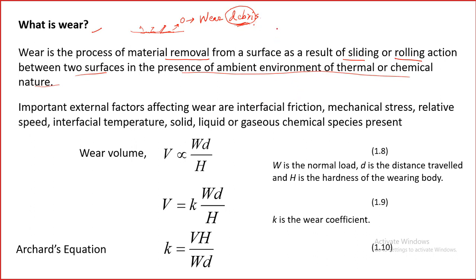So we know that wear is extremely harmful for any kind of machine because it will damage the components. Whatever bearing you have, let's say a journal bearing, if wear takes place, it will not work anymore because there will be a huge amount of vibration between the shaft and the bearing. Because of this vibration, the wear rate will go up and the whole machine may fail by fatigue. Although the machine failed by fatigue, the originator was wear. We always try to find the root cause of any kind of engineering failure, and the root cause is often wear.